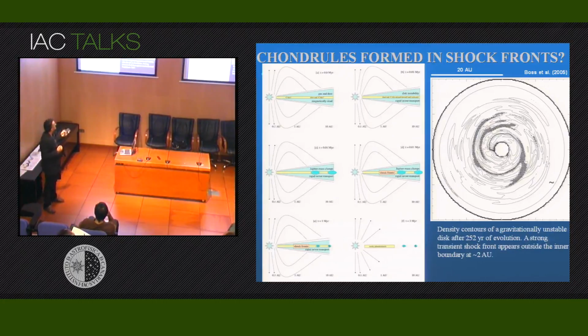promoting friction between the materials until more or less the temperature of these tiny grains, typically initially micron size, is reaching about 1,500 Kelvin, the temperature of melting of these materials, and in such conditions they are transformed into chondrules.